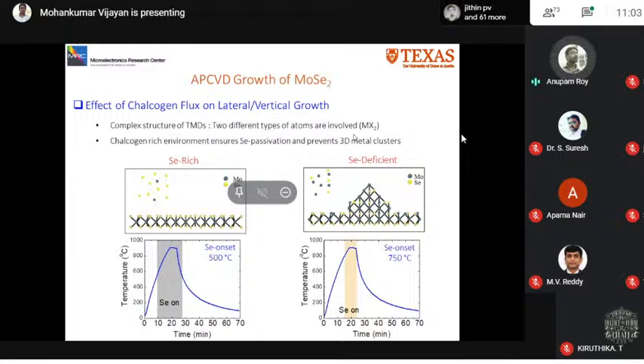Now, what will happen when we have selenium rich condition is that each moly atom that attaches at the domain edges bonds with selenium atoms first, and that will ensure a near dangling-bond-free surface formation and strictly lateral growth. On the other hand, in a selenium deficient condition, the probability of moly atoms attached to the domain edges bonding with other incoming moly atoms becomes higher because of the limited availability of selenium atoms. And this will enhance the chance of metal clustering due to incomplete selenium passivation of moly nuclei, which can lead to three-dimensional island growth. So in the next slide, I show the images on the top.